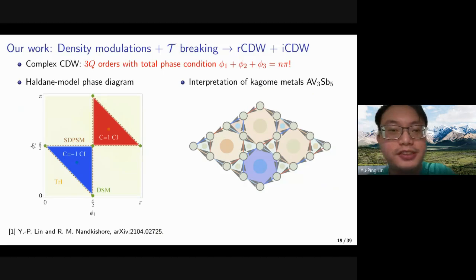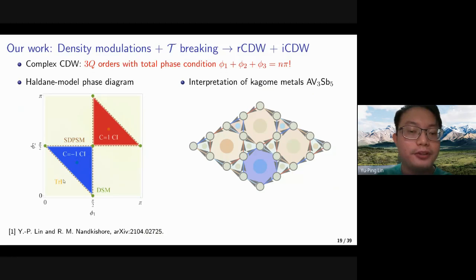So our work was that, combining the density modulations observed in the experiments and the time reversal symmetry breaking, which we also observed, we combine the real and imaginary charge density waves. And we found that this kind of complex charge density waves could realize the 3Q orders, where there is a total phase condition for the complex phases, which should be quantized. We found that there could be a Haldane-model phase diagram under a total phase condition, where we could have the trivial and Chern insulators, and also a Dirac point and a single-Dirac-point semimetals. And we will present the interpretation to the kagome metals.